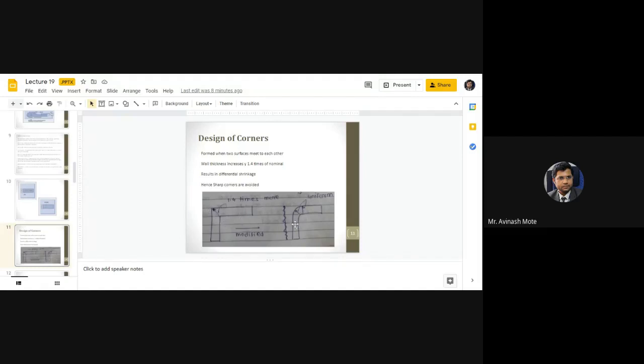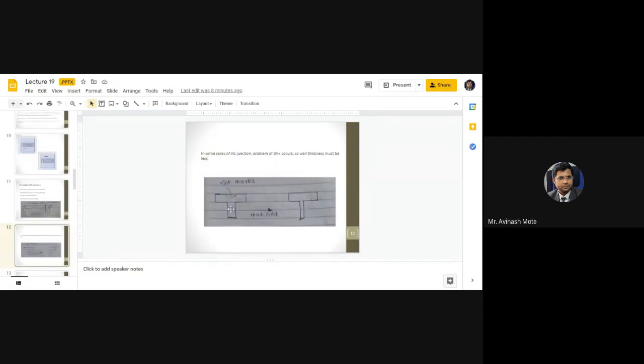So what is the solution for that? Go for this kind of wall thickness, avoid corners and maintain constant uniform wall thickness throughout the component whenever possible. Okay, so you can go for this cylindrical type or this oval type shape rather than going for sharp corners. Then here also, this is one of the cases with sink marks, because at this arm different cross section and at the vertical arm different cross section.